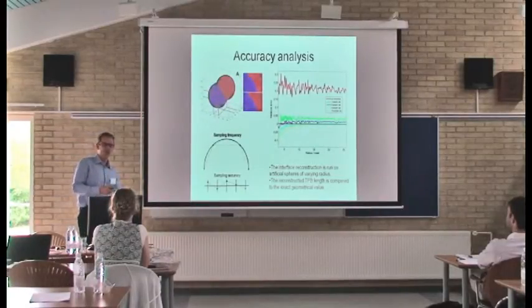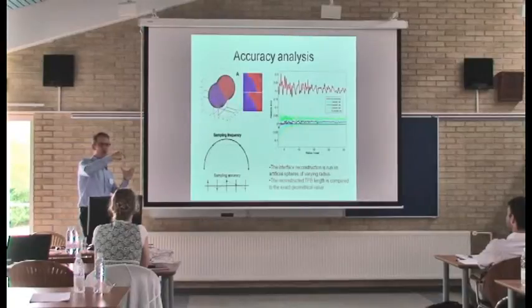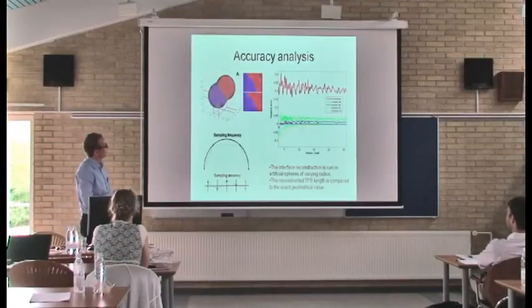And I compare this value to the true, or exact, interface boundary between such two intersecting spheres. And if you do this, you can apply different numbers of iterations. But for instance, with two smoothing iterations, you can see that you can reconstruct the triple phase boundaries in such a toy example at maybe 1 or 2% over segmentation in general.